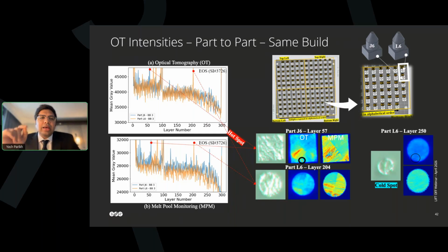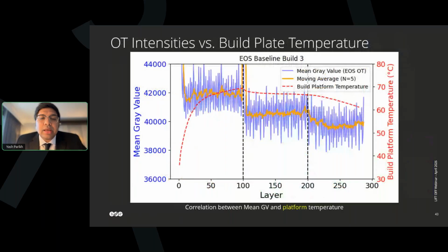So we looked at, say, layer numbers 57, 150, and 204, which showed me spikes. At 57 and 150, the spikes are believable. But at 204, I wanted to really see what's going on. So we looked at OT, looked at multiple monitoring, looked at the other modality, and we found these things are because of the spatter and because of the small particles that are absolutely shooting up the mean gray value. Go to the next one. Here's the story.